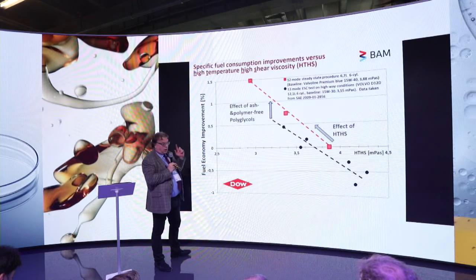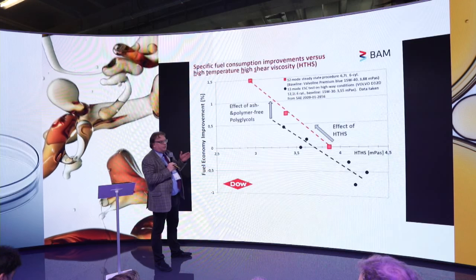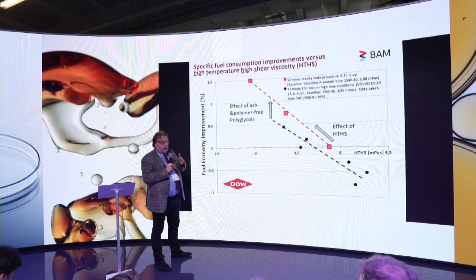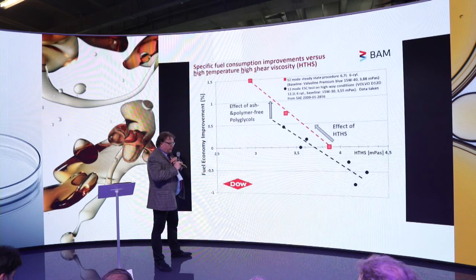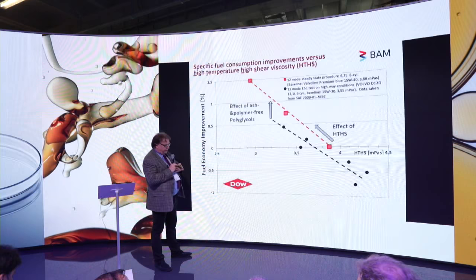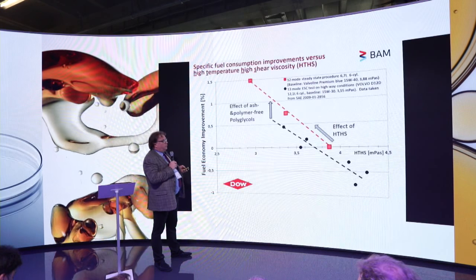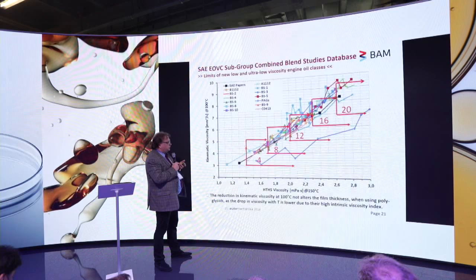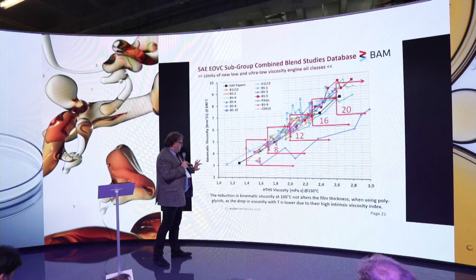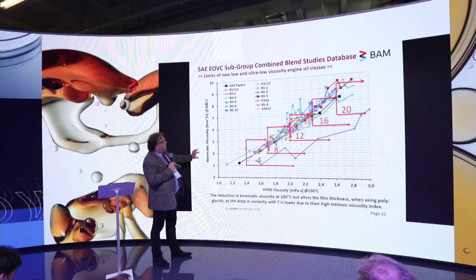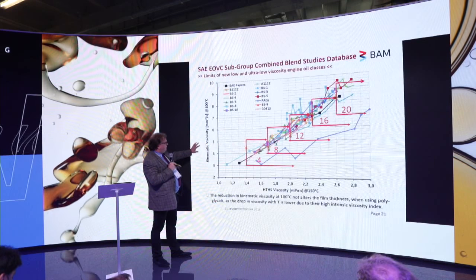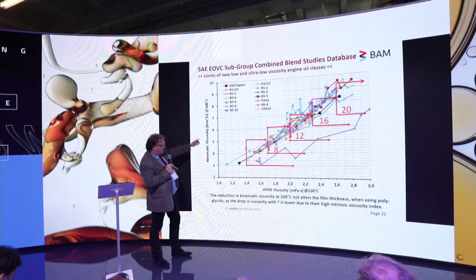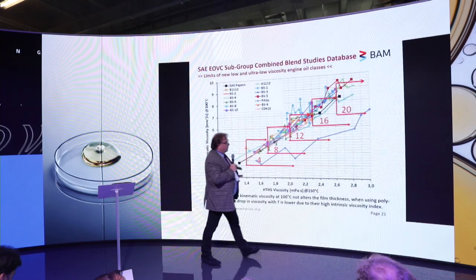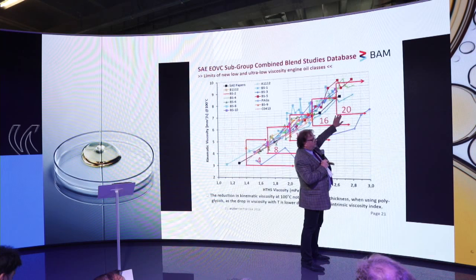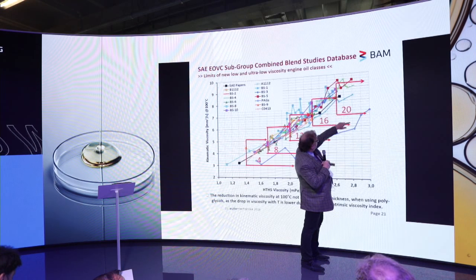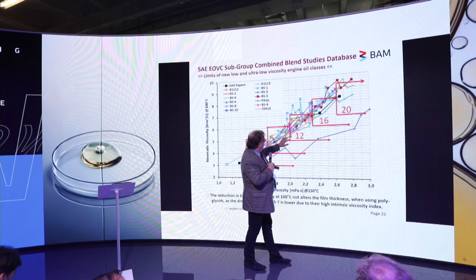And if you go here around, you see now SAE 0W-8, 12, 16, very low viscosity engine oils, and the reason is you reduce friction and you improve fuel economy. Here you see the sheen. These are blending studies. You have here the kinematic viscosity at 100 centigrade, and here's the high temperature, high shear. Maybe some know 0W-20 oils. They are in this box. 16 are here, 12, 8, 4.